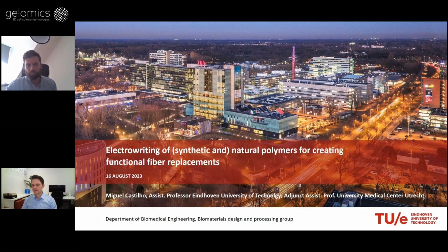Yeah, that's correct. Also from our own work, we've noticed that if you print very thick scaffolds, let's say with a certain pore size of around 200 micrometers, the bottom maybe 50, 100 layers seem to be very precisely deposited at 200 microns pore spacing, so the target spacing, but it does become a little bit less organized the higher you print.